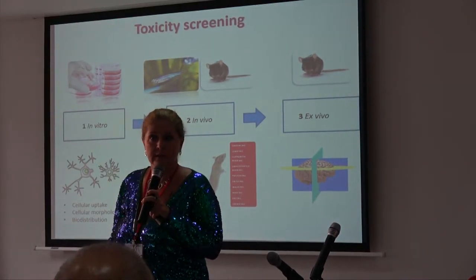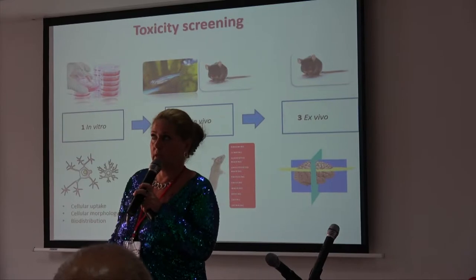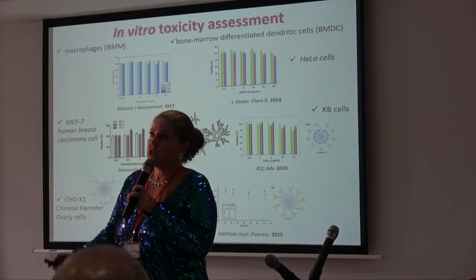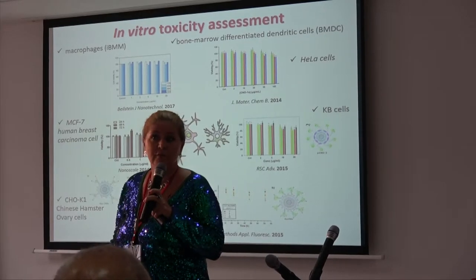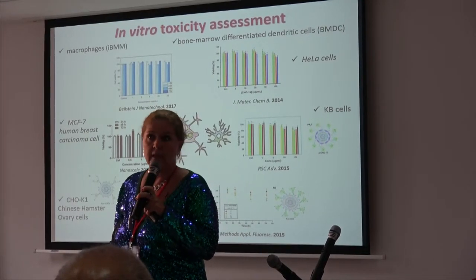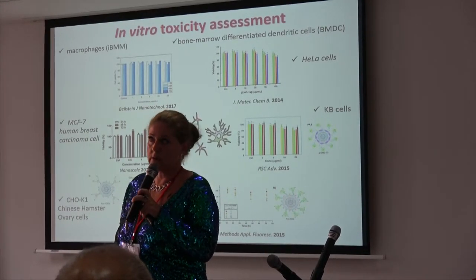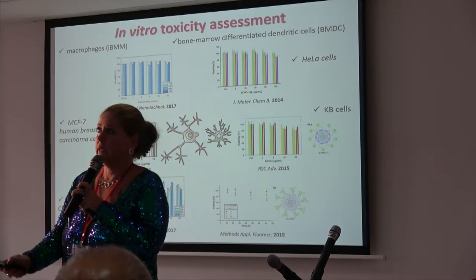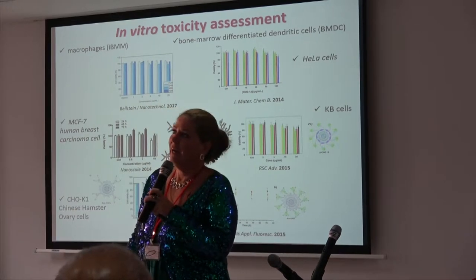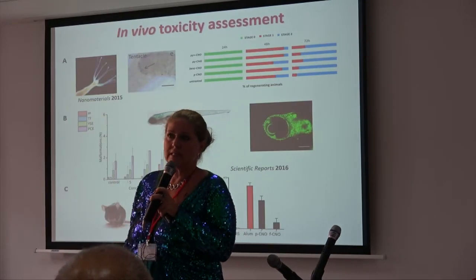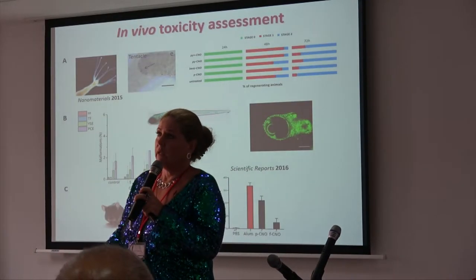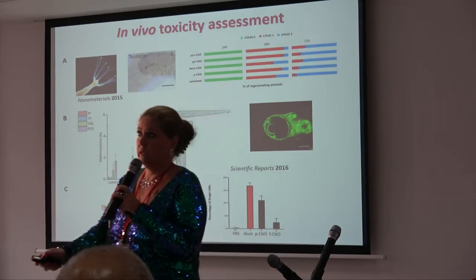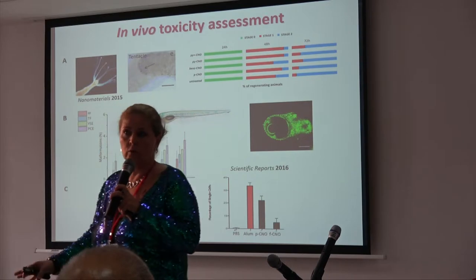We have done a complete toxicity screening starting from in vitro, in vivo, and most recently ex vivo. We have checked the toxicity profile and we can say that they are biocompatible and not toxic. We tested in many cell lines, and we also tested in vivo in Hydra, which is a freshwater polyp, and we could see uptake and no toxicity.